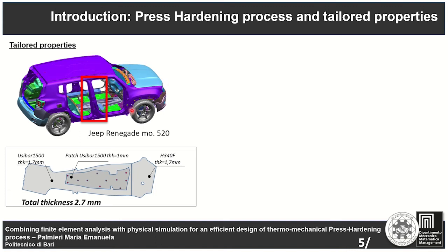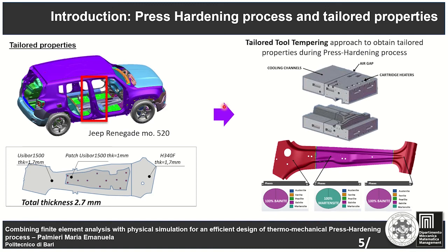Moreover, to obtain a ductile region in the bottom part of this component, a steel H340F is adopted. However, the aim is to produce a tailored component starting from a single blank without additional process steps, adopting a tailored tool tempering approach, which consists of controlling the cooling rate during the quenching phase. In particular, specific regions of the tool, die and punch, are heated. Others are cooled in order to obtain, respectively, bainitic and martensitic regions.